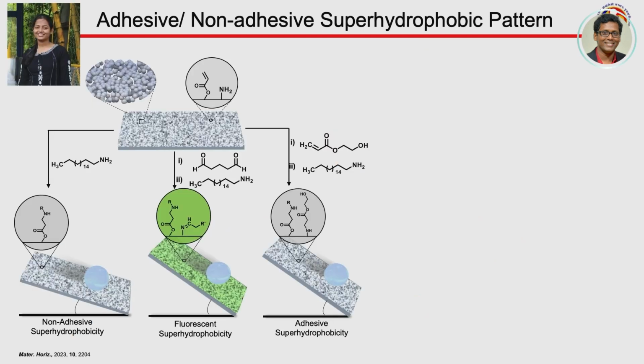So we thought, let's go for another way of modulating that. What we can do, we have taken the same porous coating. Earlier we only explored the acrylate group. Now we are exploiting the residual acrylate and residual amine both. So first, when you go for the modification with octadecylamine, you get non-adhesive superhydrophobicity, extremely repelling above 150, and the rolling angle is less than 10, around 4 or 5.